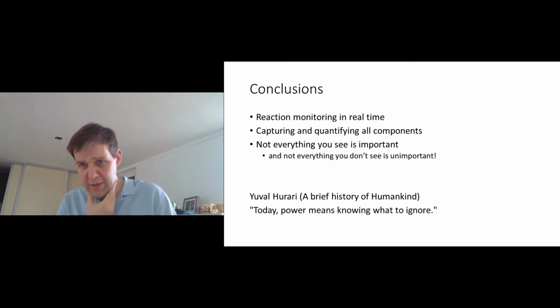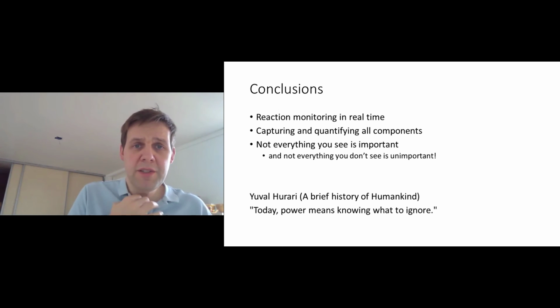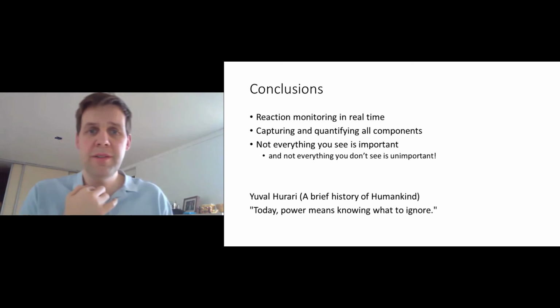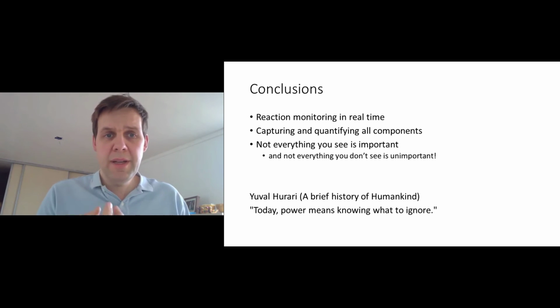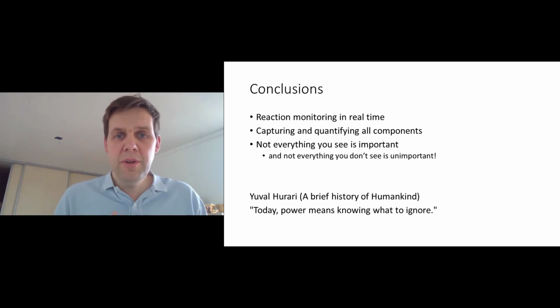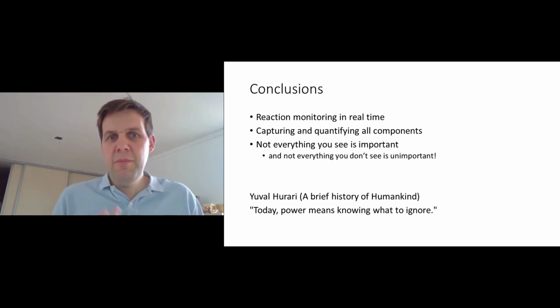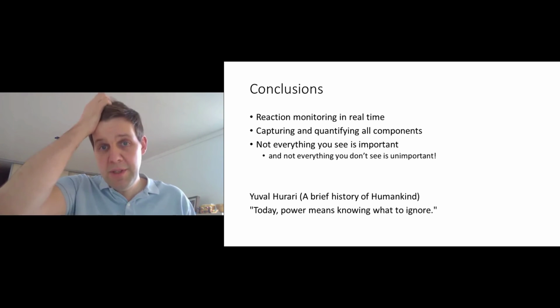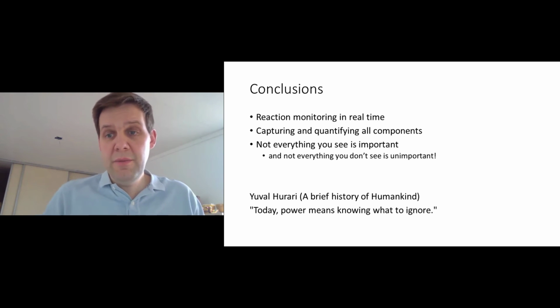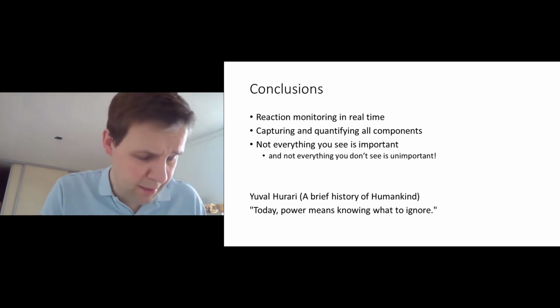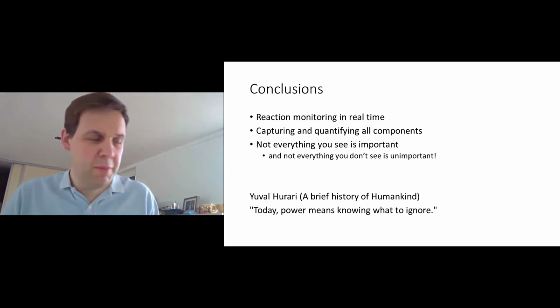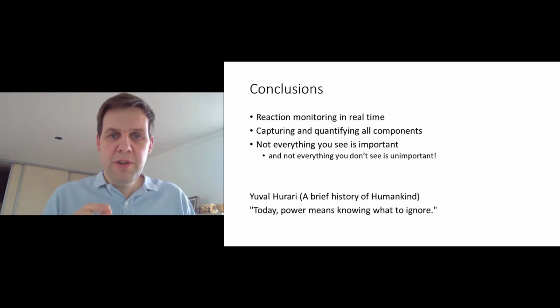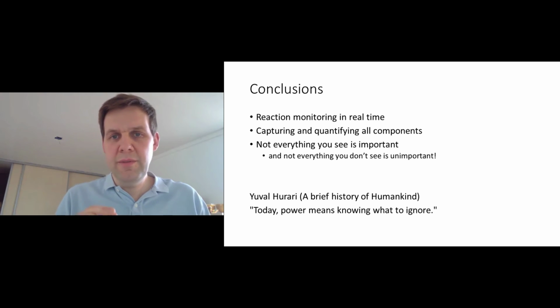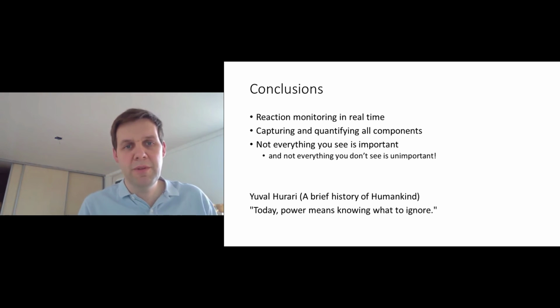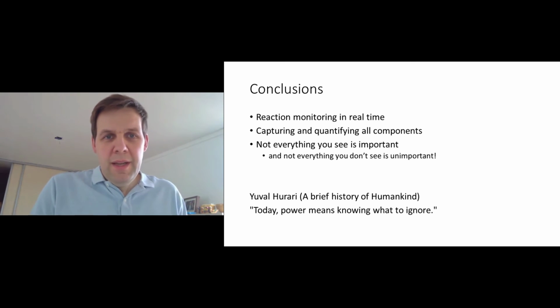So, to give you a few conclusions, and sorry for going a little bit over time. I hope to show you that monitoring reactions in real time can give you information which is essential to understanding how your reactions are working, how the complexes or the catalysts you're using are behaving. And it's important to use as many different spectroscopic techniques as you can, but also, especially with Raman spectroscopy, it is not one technique. There are many flavors of Raman spectroscopy, and if we use, for example, resonance enhancement, and we go for very high time resolution, we can actually get information which is not really accessible by any other approach. And the key thing about Raman spectroscopy, and I'm a very big proponent of Raman spectroscopy for this reason, you get structural information in real time. So UV-vis spectroscopy is very useful for following the changes that happen, but the structural information from Raman spectroscopy is second to none.